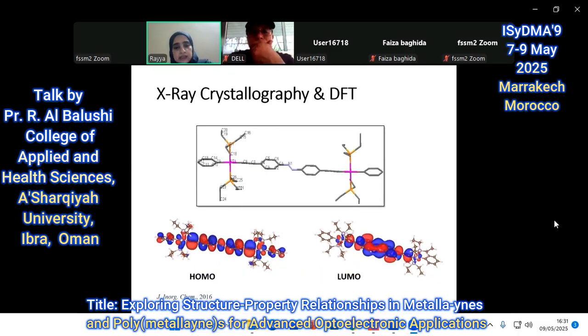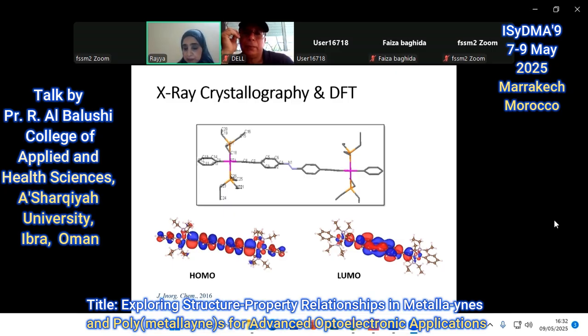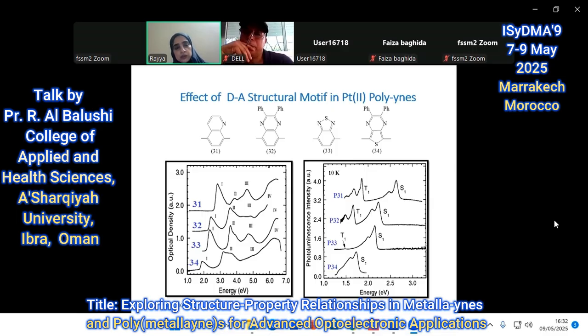This is an example of a crystal structure of one of the model compounds which I studied, and usually we support our experimental data by theoretical calculations. Here this is an example of the HOMO and LUMO. Having information about the conjugation, since we have a conjugated system, gives us information about the delocalization. Once we have a polymer with a big chain, the delocalization will be over a larger chain, and with a higher extent of delocalization, they will be better for applications in optoelectronics.